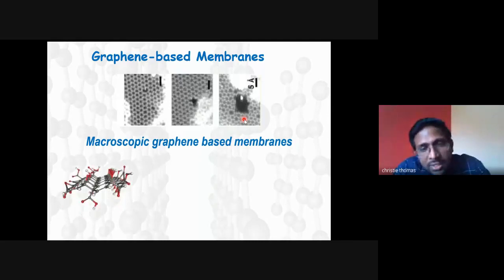And there comes graphene oxide. What is graphene oxide? I know at least a few of you might be working on graphene oxide because it's easy to synthesize in a lab scenario. Graphene oxide is nothing but oxygen functional groups attached to a graphene sheet. About 40 to 60% of the graphene oxide sheet will be functionalized. So you can imagine it as pure graphene parts as well as oxygen functionalized portions. The beauty of graphene oxide is that it can be produced on a large scale.